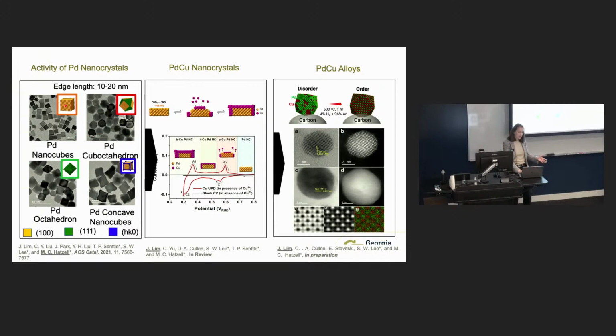And so he created these nanocrystals where we had 100 facets, so these are nanocubes, and then these cubooctahedron, which had both 111 facets and 100 facets, these octahedron, which had the 111, and then also concave nanocrystals that had basically highly faceted surfaces. And we benchmarked all of this against palladium polycrystalline catalysts. And so this was the first thing he looked at.